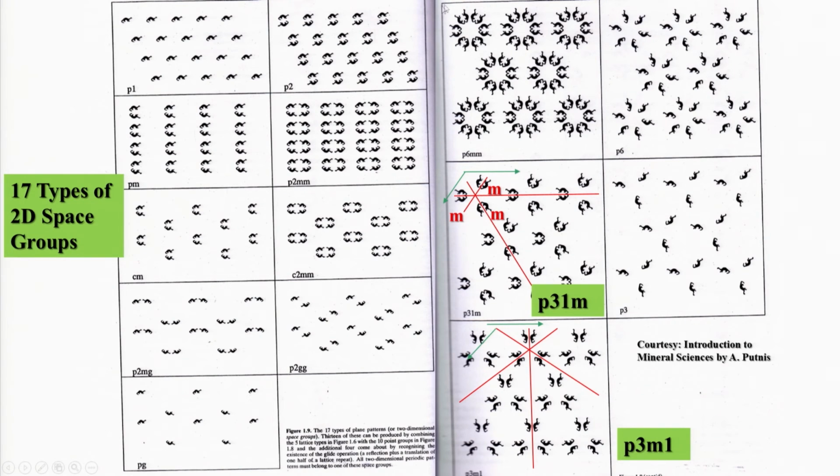They occur in 2 sets, 3 in number. That is very nicely shown here by the orientation of one set of mirror planes, another set of mirror planes. These 3 you can see, and you can also think of another set of mirror planes at an angle of 30 degrees between them. So you have a very simple situation here of 6mm, and this is the primitive lattice. In one node here, it is translated along this A, it is also translated along A, and if this angle is 60 degrees, it develops this hexagonal plane lattice here.